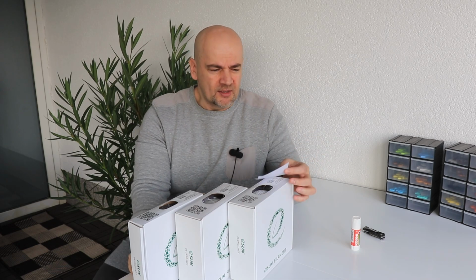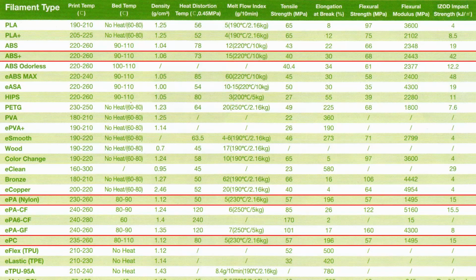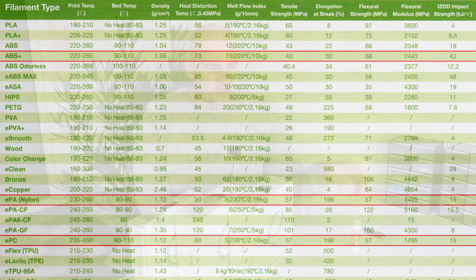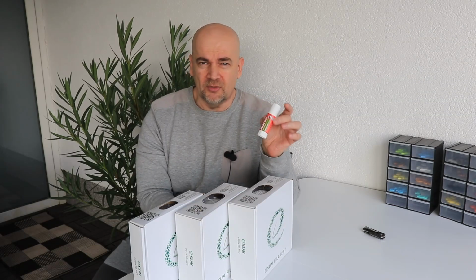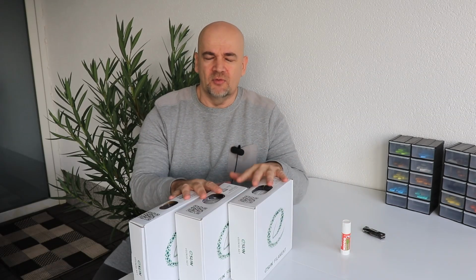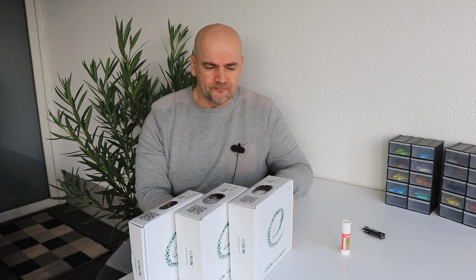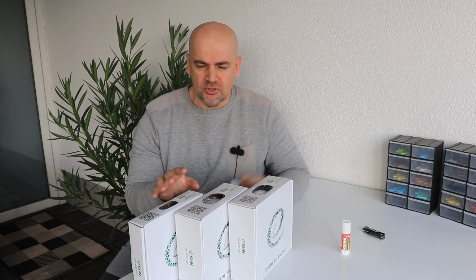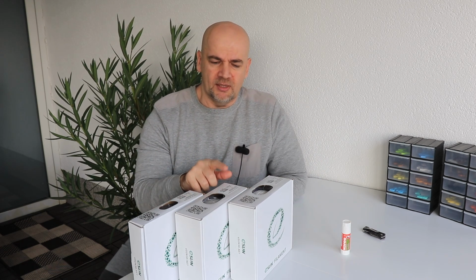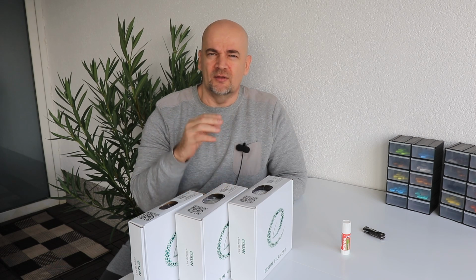So from their website I collected some main information. The printing temperature for ABS Plus is between 220 and 260 degrees Celsius. The bed temperature is between 90 and 110 degrees Celsius. And in all three cases I will use a glue stick for better adhesion, and they have to be printed inside an enclosure. I'm not sure about the polycarbonate, but I know that the nylon needs to be dried.